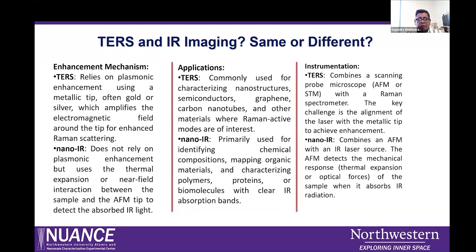In the Raman, the enhancement mechanism is based on plasmonic enhancement, using a metallic probe. We use a very special probe, often coated with gold and silver, and that can amplify the electric field. Okay, and that results in a signal enhancement by a factor of 10 to the 5 or 10 to the 7. In the case of nano IR, it is basically the thermal absorption. Okay, and that creates oscillations, and then the probe is there to detect those oscillations. With TERS, as I said, you can use nanostructures, semiconductors, graphene, carbon nanotubes. TERS has a limitation that the sample thickness has to be just a few nanometers. Okay, so the sample prep is very critical in the case of TERS mapping.